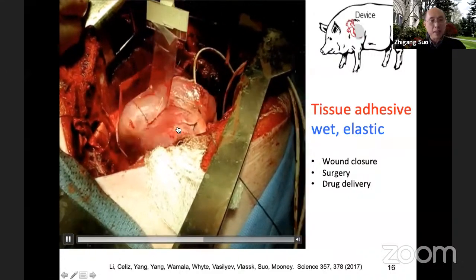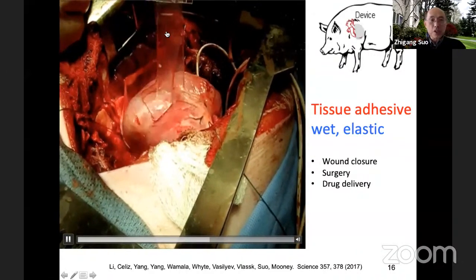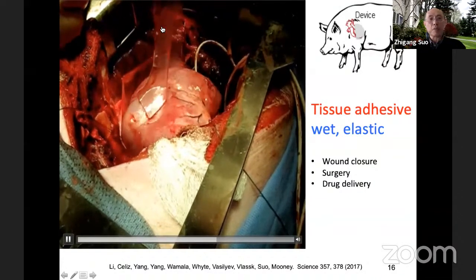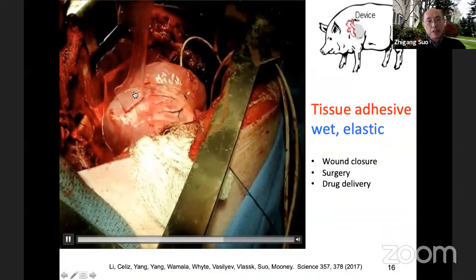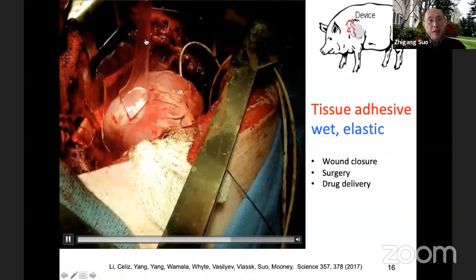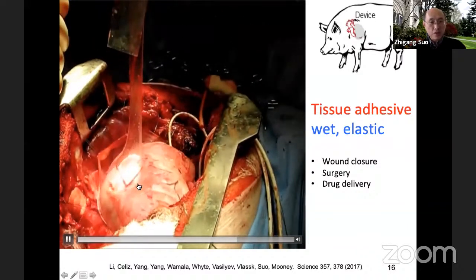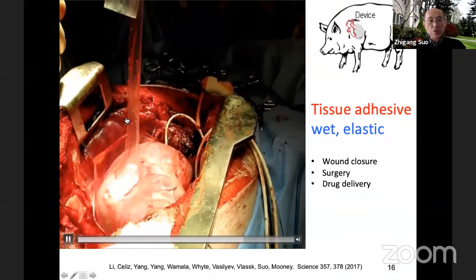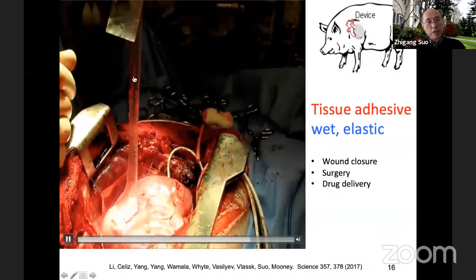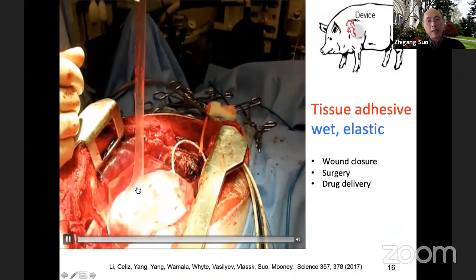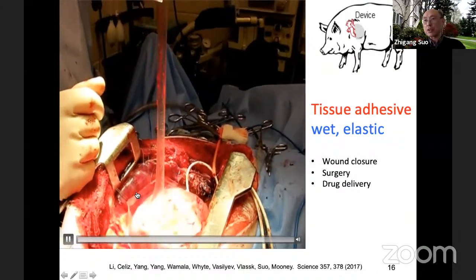This gel itself is very tough—its self-toughness is more than 1,000. And you can see adhesion is wet and very elastic, so it's heart, still moving, and adhesion is strong. You can see you can use this as a spring, a gel as a spring. The force is very high. We measured adhesion toughness to be about 1,000 joules per meter squared.